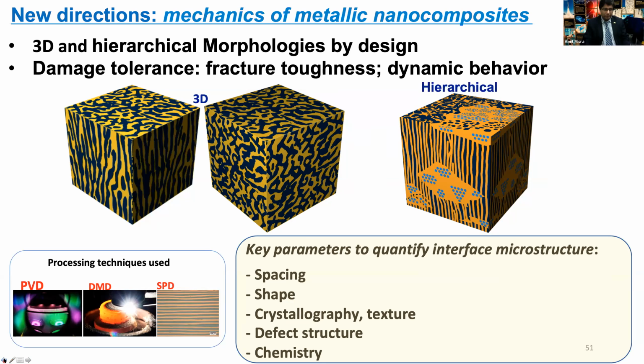So a good point. What we do is the tension test from FIB lift-out that I showed in one slide. We measure the yield strength of the hierarchical microstructure without the notch. So that's what that sigma y is meant to be in that equation. And we have measured it both by compression and by tension. Ideally, it should be by tension, but with tension, sometimes you get more scatter. And so we did compression also to compare, just to see how much difference you get.